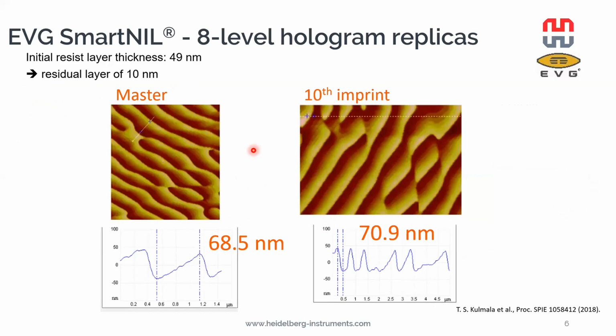As I said, we sent the sample to EVG for replicating, and they made 10 working stamps out of this master. Then they measured the 10th imprint and compared the AFM image of that to the original master. They could practically see no degradation of the depth of the pattern, so it is pretty much the same.